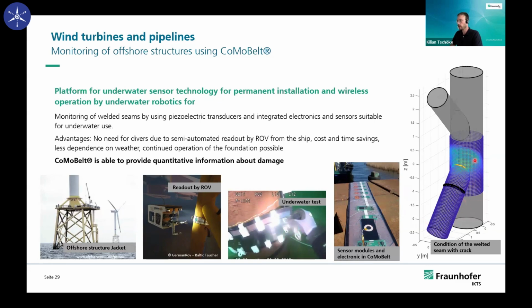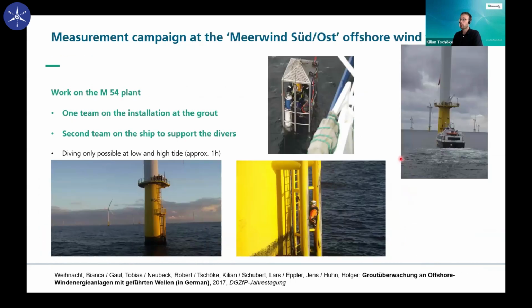And as you can see on the right side, this is an example where we used two sensor belts. You've seen this example in the previous slides. It's a kind of tomography, as the doctor does if you go to X-ray tomography. The main signal processing idea, the main algorithm, is the same, and this can give you really quantitative information about damage positions and damage sizes. Of course, you need some more sensors than only two, but it can give you really detailed information about this. Yeah, one really interesting question is, okay, we are talking about work underwater, and water is, of course, a damping material.